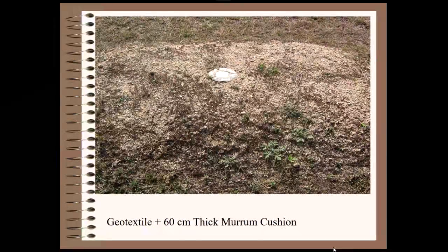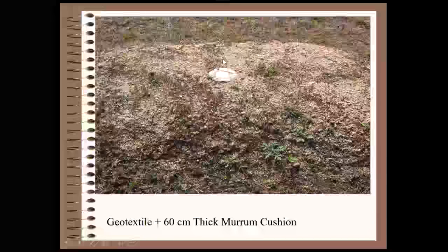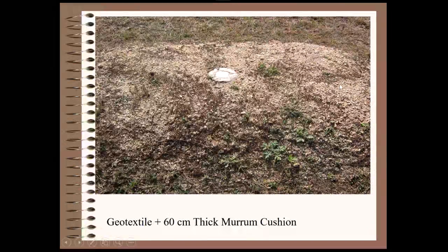See here the magic. Geotextile I have used directly on the prepared subgrade. Grass is removed, then a geotextile is placed, then a 60 centimeter thick Murrum cushion is placed. No cracking is reflected to the surface. And I don't think that no cracks are formed in the subgrade, but because of the high tensile strength of the geotextile, that crack is not able to reflect to the surface. Okay, so that is how geotextiles can definitely be provided within these systems to control reflection cracking to the top.